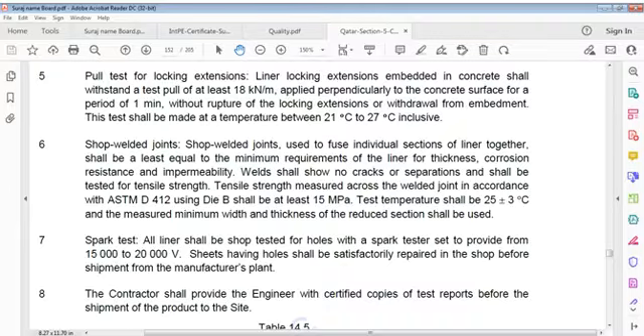Weld shall show no cracks or separations and be tested for tensile strength. Tensile strength measured across welded joints in accordance with ASTM D412 using Die B shall be at least 15 MPa.